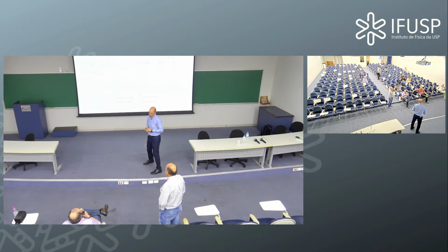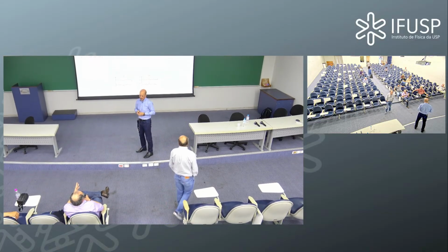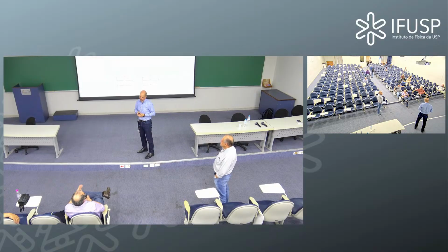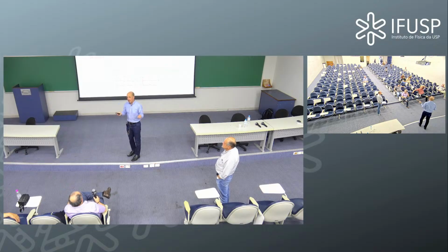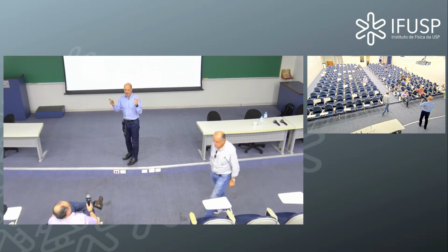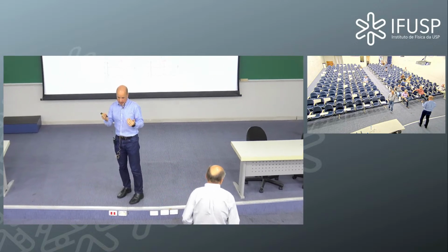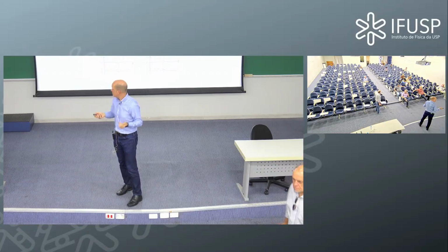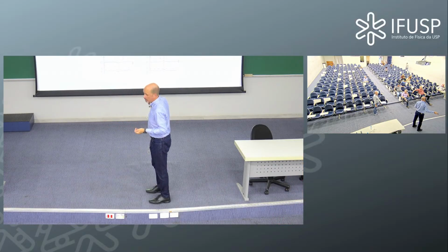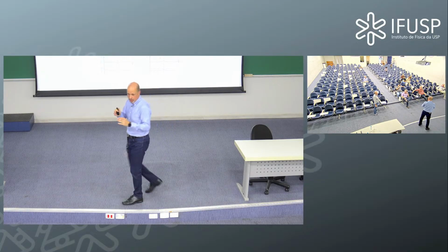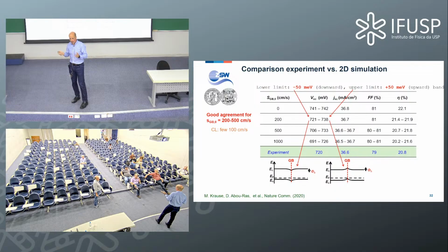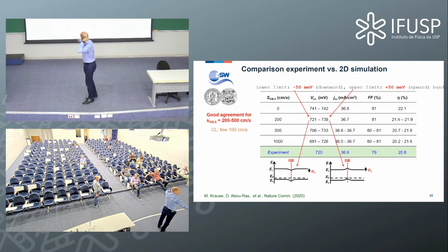This slide, when you make the experiment with an actual 3D system, and you make the comparison with the 2D system, how is it reasonable? Normally, I can use the same grain boundary parameters, for example for the recombination, and look at how well the experimental PV parameters can be simulated. We don't change anything else, the material. We only change the dimension of the model. Then we can see how close I can get to the PV parameters actually measured on the solar cell.